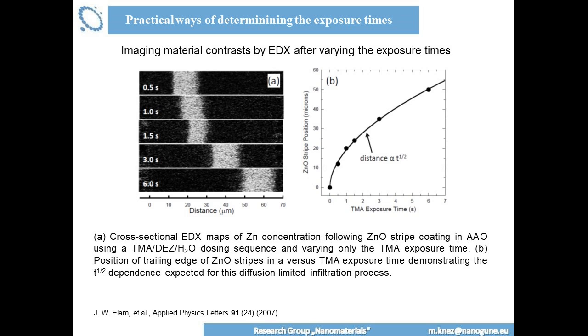These are the pores. Now, if you expose to TMA to grow aluminum oxide first, so first you have TMA, and then after the TMA pulse, because this part of the surface is saturated with TMA, it's blocked, you expose then to DEZ, the diethyl zinc. The diethyl zinc cannot bind to this part of the pore because it's already covered with aluminum. That means it's forced to deposit later on in the back parts of the pore. Now, if you do this sequence, you can do various exposure times, first with TMA, and then look in the cross-section with EDX scanning. You can look into the location of the diethyl zinc.